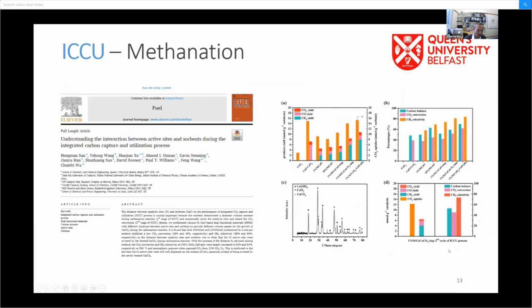After 8 or 9 cycles, you can see the conversion of CO2 is almost 100%. The methane selectivity is almost 100%. So it's all 100% at that point. So we are not quite sure exactly what's going on there. So maybe some further study can be done. So very high selectivity, high conversion.